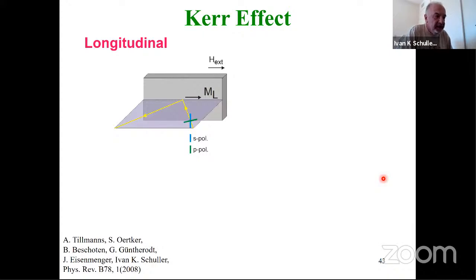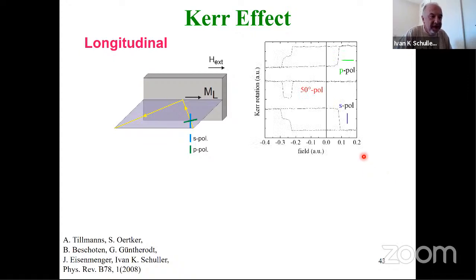So there it is, for instance, the longitudinal magnetic moment that measures the magnetic moment M along the field direction. And so you can see here the Kerr rotation as a function of field. And depending on whether it's perpendicular polarized or parallel polarized, whether it's P polarized or S polarized, the hysteresis loop reverts. But there's something very weird that happens here. There is a step in one side of the hysteresis loop, and there is no step in the other side. Remember, I told you that all magnetic materials known to man have symmetric reversal. There is nothing that distinguishes up from down. But here, there is something that distinguishes up from down.